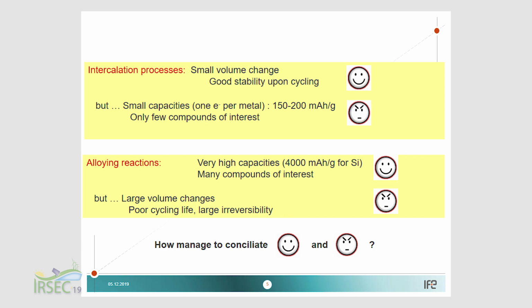The comparison here is based on two parameters, volume change and capacity, which are important factors either in solid-state or in normal batteries. Intercalation materials usually have low volume change, which is good because the volume change is small. However, their capacity is usually around 200 milliampere-hour per gram.